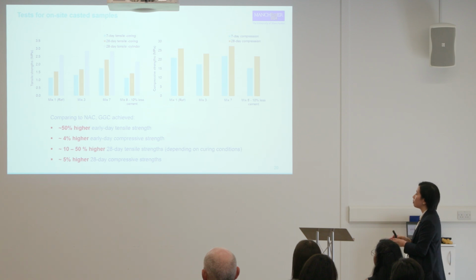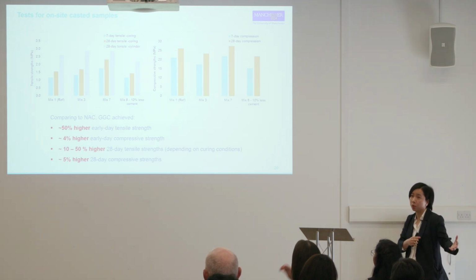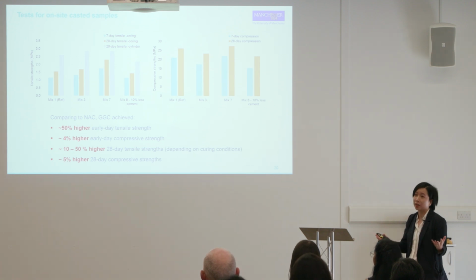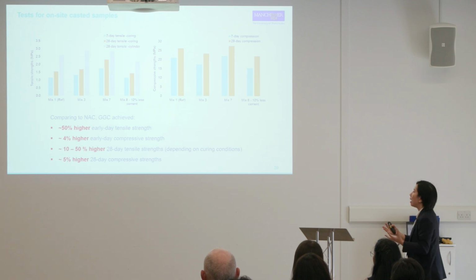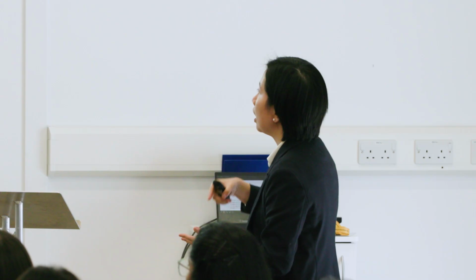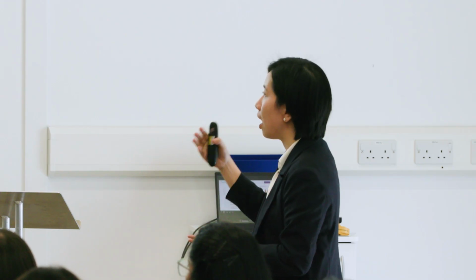In general, the specimens that were cured in a lab condition with controlled moisture and controlled temperature got higher strength than the specimens that were cured in the open air condition. That is what we expected because the whole activity was carried out in the winter. And what we were happy to see is that compared to the natural aggregate concrete, the graphene green concrete actually enjoyed 50% higher tensile strength, even though in this case the improvement in compressive strength is less significant.